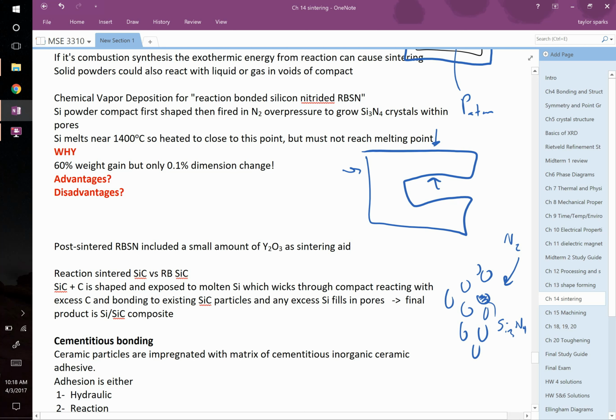What can happen is you will form it most rapidly at the surface. That's where it's in contact. It can actually form a gas impermeable layer of silicon nitride and then block off the stuff inside. So you might end up with a graded material where you have silicon nitride at the edge, but once it blocked itself off to further nitrogen gas, you're done. And there could be pores left over on the inside. It'd certainly be unreacted silicon. It's not a very good scenario.